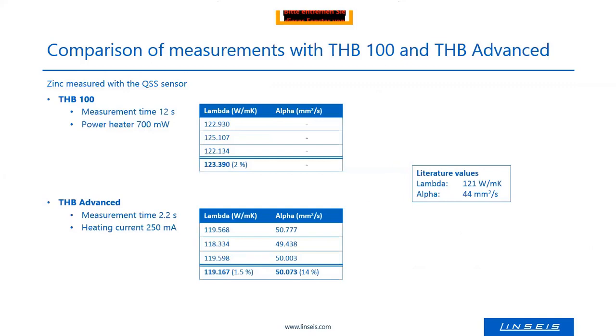But still, it's okay, I would say, for the lambda, for the THB 100, it's still good: 2% uncertainty or deviation. For the THB Advance, it's better, it's 1.5%. And also we can measure alpha, but it's starting already to get higher in uncertainty. But at least we can measure it, which was not possible at all with the THB 100.